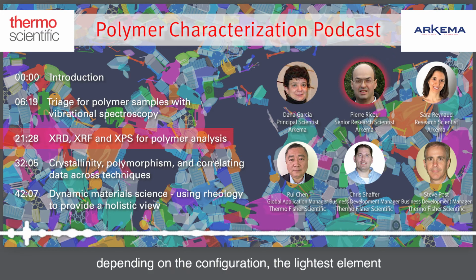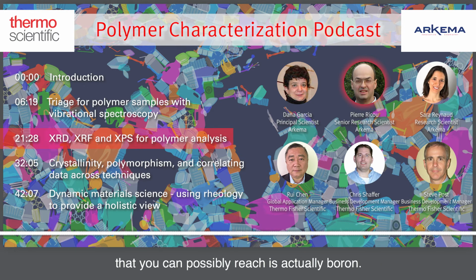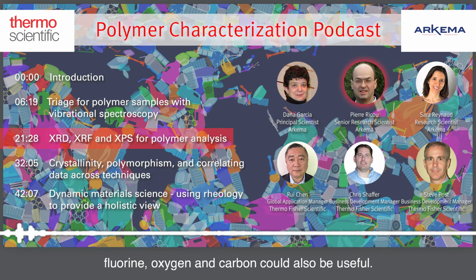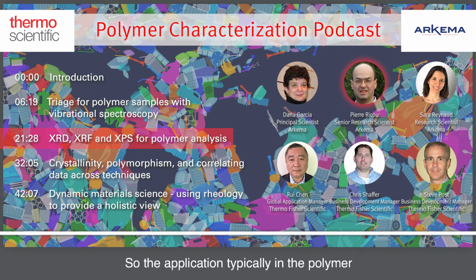And typically with XRF, depending on the configuration, the lightest element that you can possibly reach is actually boron. So for glass manufacturing, something of importance. For the polymer field, of interest is anything that starts, I would say, minimum at least at sodium, and sometimes, depending on your application, if you can go a little lighter, fluorine, oxygen, carbon could also be useful. So the application typically in the polymer field, the plastic industry, is 2 big themes, I would say. You're either looking at trace metal contamination, and you want to understand why a part has degraded, or make sure that your production is within specification, so kind of a QC support type aspect.